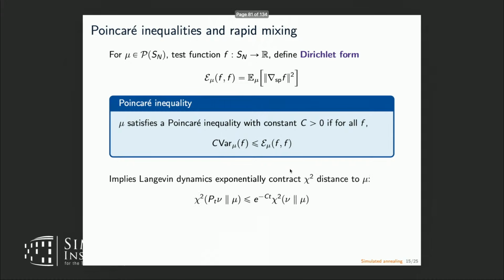And this Poincare inequality turns out to imply rapid mixing even from a worst case initialization. So it turns out to imply that the chi-square divergence of your sample to the target will contract exponentially. So the way to read this is nu is the measure that you initialize from, and pt nu is the measure you get from that initialization running Langevin dynamics for time t. So this says that your chi-square divergence will decay exponentially. So then if this holds with a constant c that's not too small, then this implies that even from a worst case initialization, you'll mix rapidly.